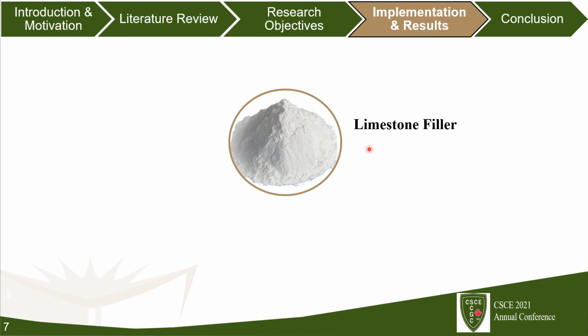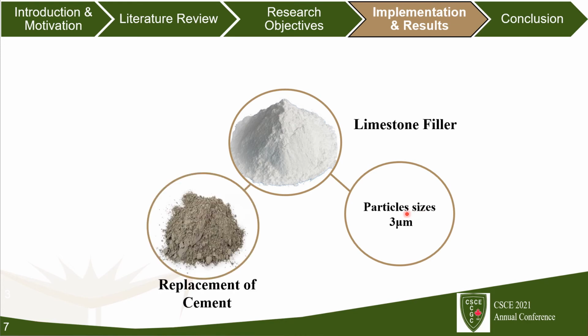Limestone filler with a particle size of 3 micron was used as a partial replacement of cement to make it more sustainable, with a percentage of 5, 10, and up to 15%.